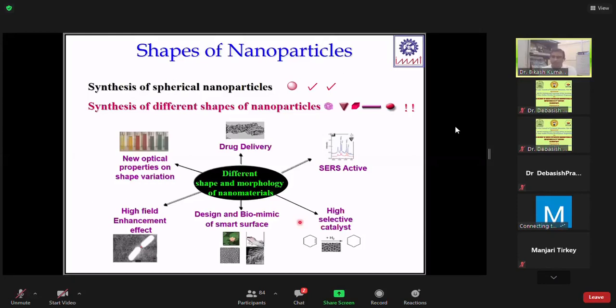And you can design and biomimic some smart devices. Like you can construct a lotus leaf by constructing different shapes for hydrophobic surfaces, and you can grow nanowires and flexible polymeric wires that give a very hydrophobic nature. So by different shapes, you can biomimic smart surfaces. And also you will have a highly selective catalyst compared to the spherical. In heterogeneous catalysis, where the nanoparticle surface is used as a platform, the molecule interacts with the surface and bond making and breaking takes place. When different shapes come into the picture, that will enhance the catalytic activity compared to the spherical shape. The support of this different shape will be better compared to spherical.